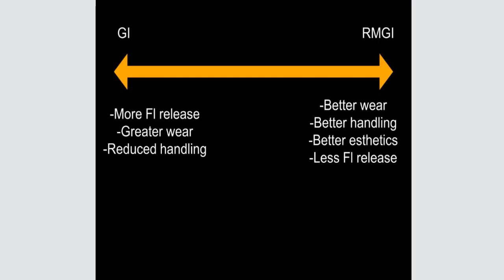So glass ionomers originally, as they first came out, were traditional glass ionomers, full glass ionomers, and had a lot of fluoride release, but they wore pretty significantly, especially when we're talking about using glass ionomer cements as restorative material, mixing them up and loading them into a lesion. They wore pretty greatly, like upwards of 70 plus microns a year, which is a lot. And they just didn't handle very well, which is kind of the experience I had with my very first restoration, right? I just couldn't handle that material well to put it where I wanted and keep it there.